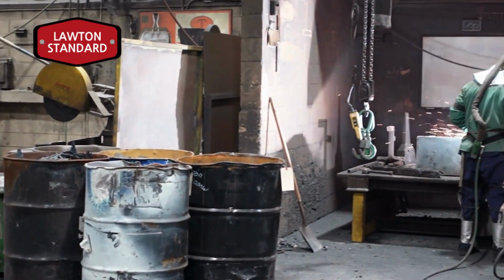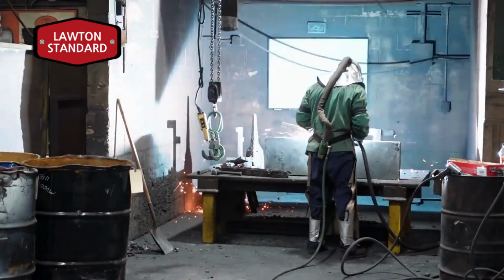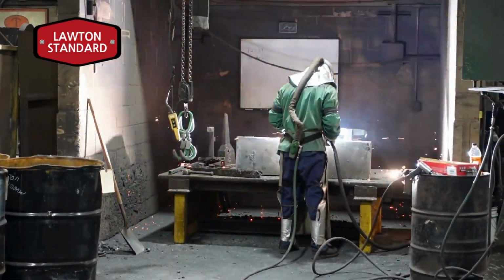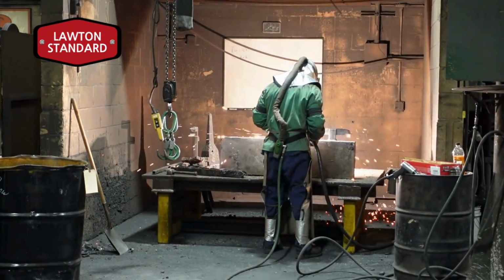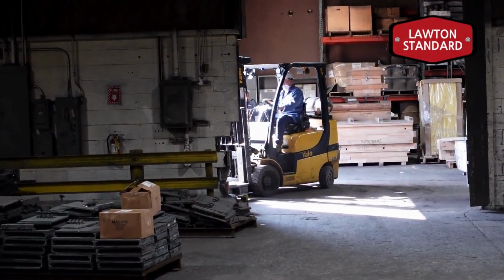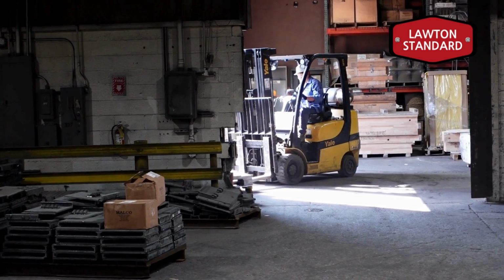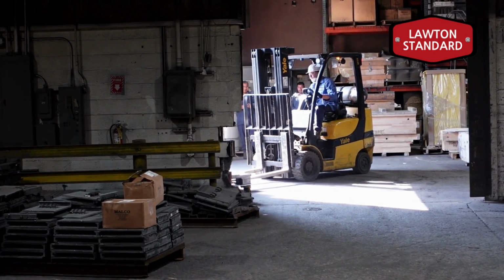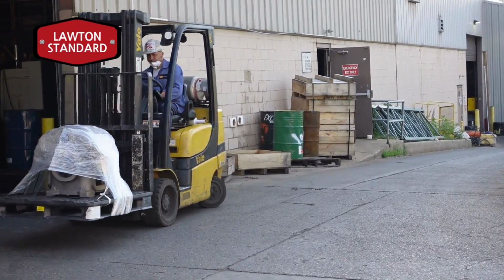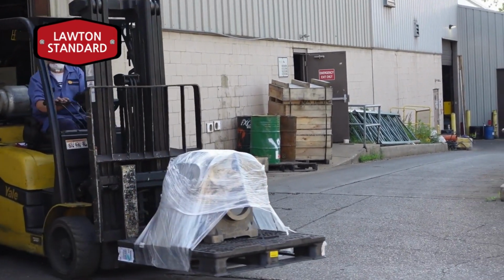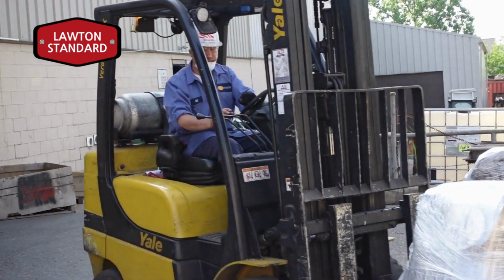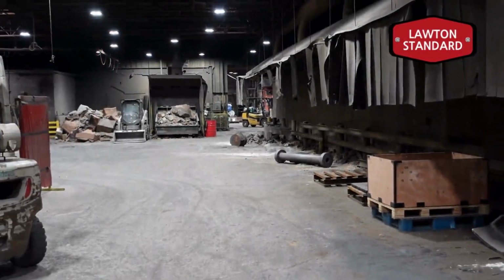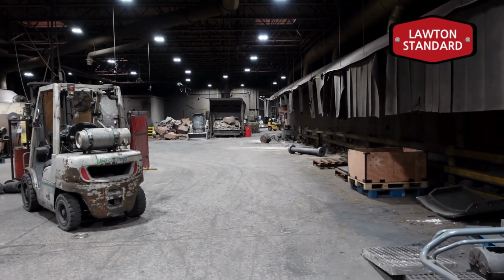Other thing I would add is it's very sensitive to heat, too. Thermal gradients in the part can very easily cause these things to rupture, these castings. So I've seen it happen before. Guys have knocked castings off of their grinding tables, and they've busted. I've seen guys go in with the fork truck during shakeout. They pick the casting up by accident, and I've seen them break when they fall from the fork truck. I've seen them be hit by the fork truck and break, just the forks going into it. It is very crack sensitive, especially after shakeout.